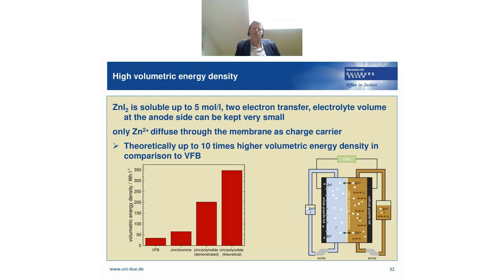So in theory, but really only in theory, we can expect almost 10 times higher volumetric energy density in comparison to the all vanadium flow battery. This is shown also in the graph on the left side, where we have on the y-axis the volumetric energy density in watt-hours per liter. Here, starting with the vanadium flow battery, then zinc bromine, zinc polyiodide has been demonstrated, and zinc polyiodide in a theoretical calculation. In theory, we could reach up to 350 watt-hours per liter, and this is really quite a lot. Then we are in the league of lithium-ion batteries almost. So that's a good motivation for doing research in this kind of battery.